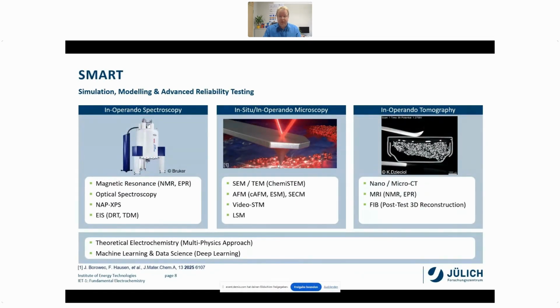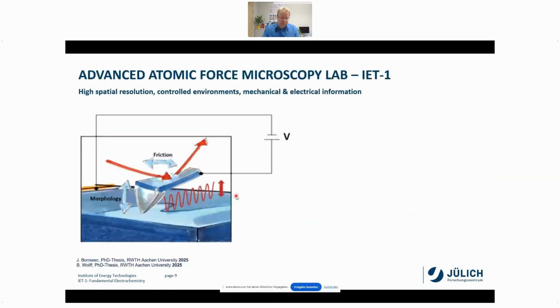We'll focus today on atomic force microscopy, especially electrochemical atomic force microscopy, but we can also do in operando tomography. And in atomic force microscopy, we basically have a cantilever with a sharp tip, and there we record the deflection of this tip, horizontal as well as vertical deflection, so we can get information about morphology and topography of a sample, but also about the friction from the torque of the cantilever. And Inhi will explain that in a second even better. But you have also the possibility to put that under different conditions. So you can measure electric currents, but you can also put it directly in an electrochemical cell.